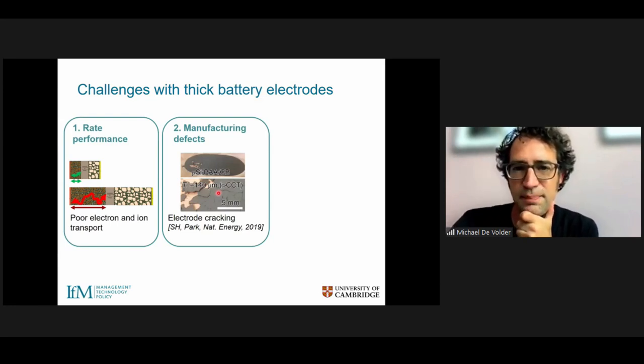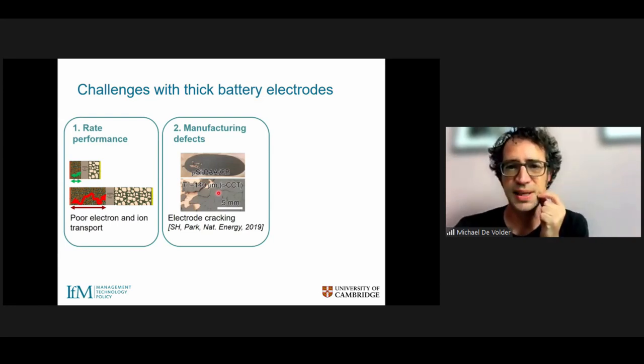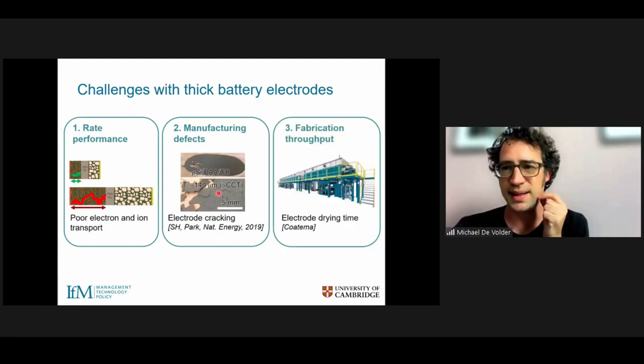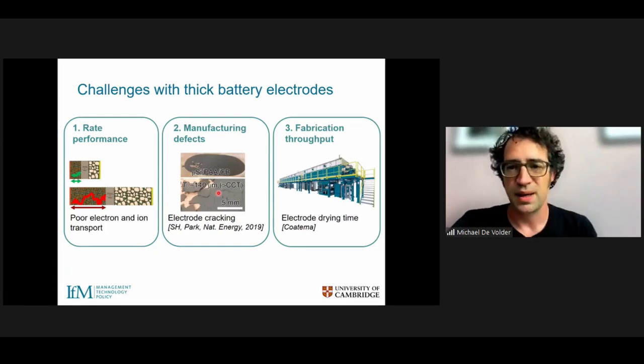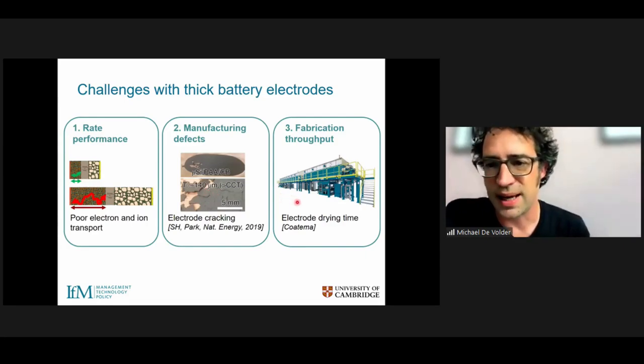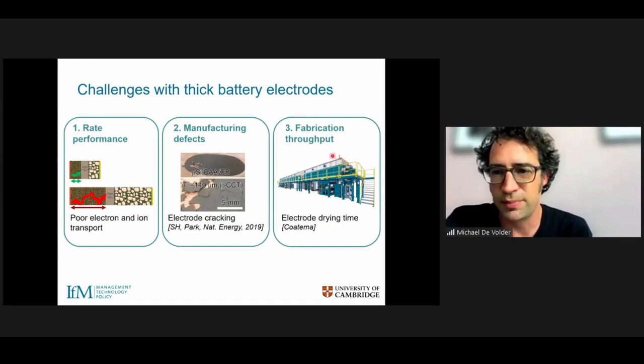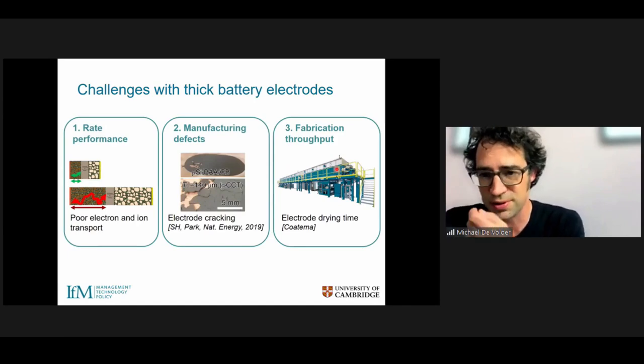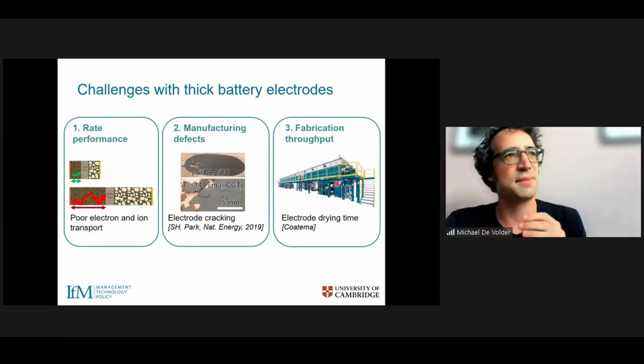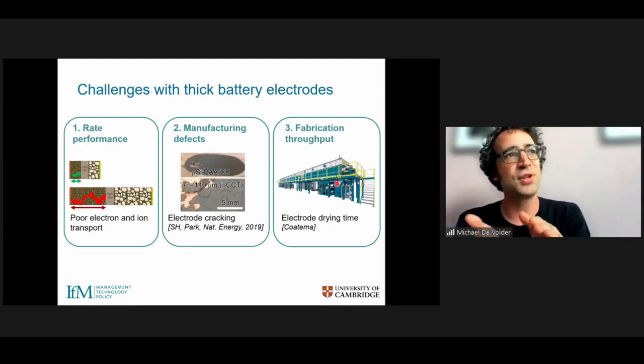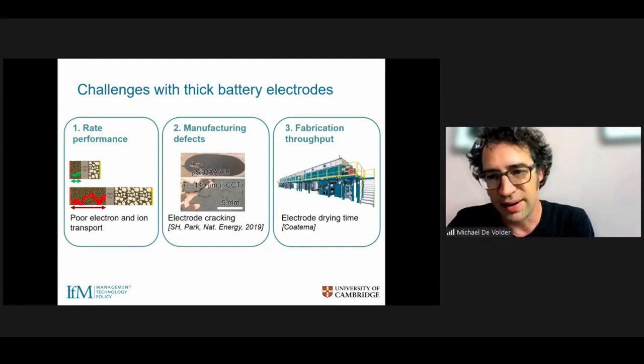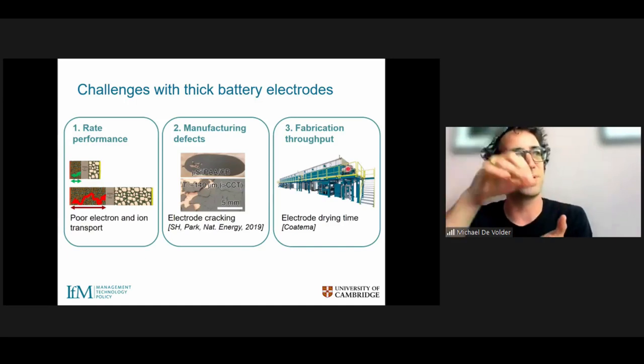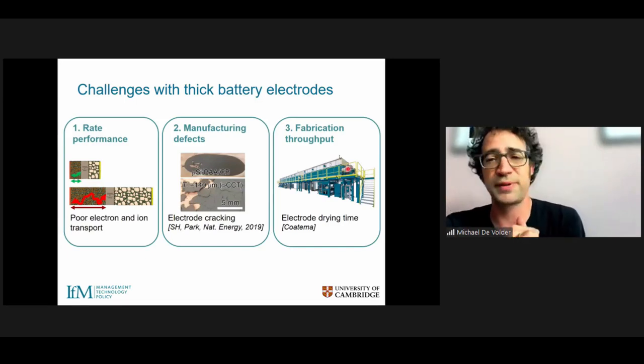And then the final big challenge with coating thick electrodes is that drying the electrode is a very energy-intensive and slow process. So to explain that, I've added a picture here of what a commercial manufacturing line for battery looks like. So this is called roll-to-roll coater. And in the beginning of this line, you have something that's similar to an aluminum foil you would use in the kitchen, which is being unrolled. At the top of the machine here, you squirt some slurry containing the battery materials on top of that foil.